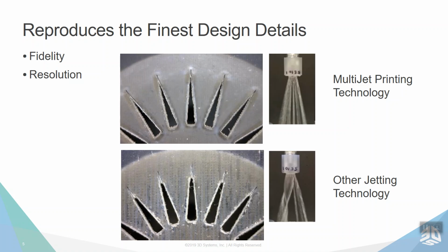And you see here the result in this comparison between MJP and a competitor. You see the holes on this shower nozzle in the top photo are perfectly triangular all the way up to the tiny tips, while the competitor's tips are sealed and closed off. The result is that you see the spray of water coming out of the MJP nozzle straight and clean, while for the other competitive system it's very skewed, a nice indication of overall resolution here.